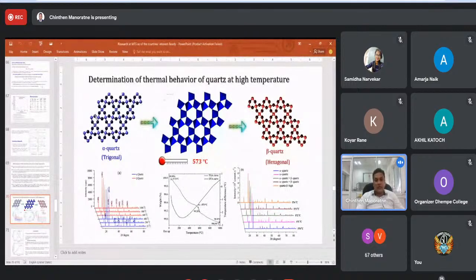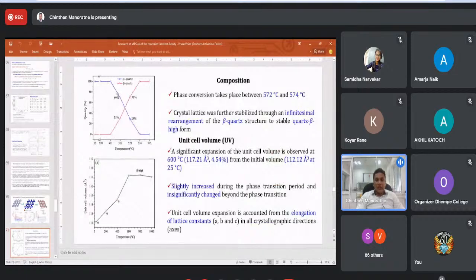Now this is alpha quartz at room temperature, and this is beta quartz, and it goes through an intermediate product. This is the corresponding XRD spectrum for alpha quartz and beta quartz. We did some thermal analysis where you can see that at about 570 to 573, this conversion takes place. For that we used the heating attachment available with the XRD, and when you increase temperature, we narrowed down the scanning temperature from 570 to 575, and you can see that around 572 this conversion takes place. While alpha quartz composition reduced, the beta quartz is increasing.